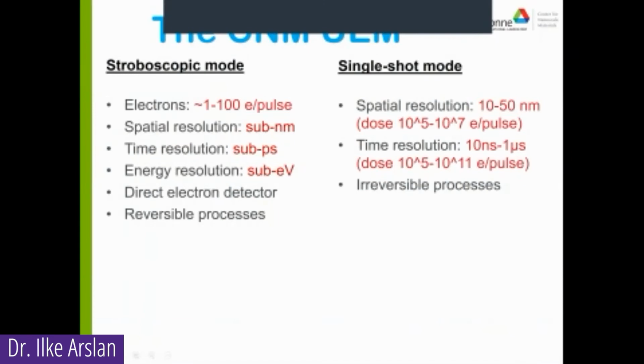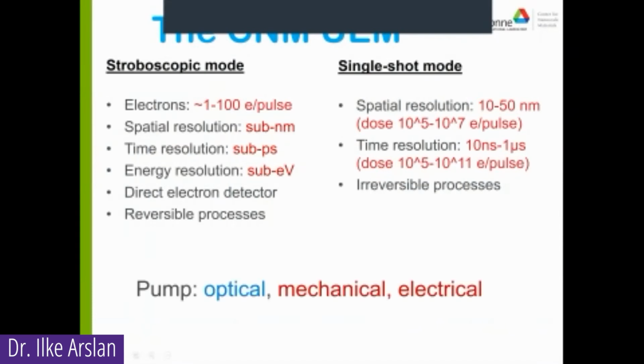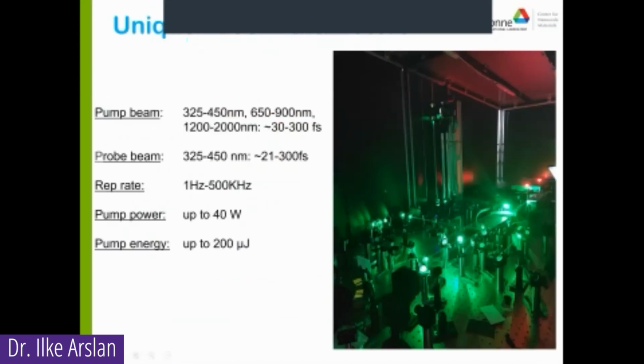But I'll just finish up by telling you that we can operate the UEM in these two different modes, but we're operating in stroboscopic mode. So we are looking at around 1 to 100 electrons per pulse. We can get sub-nanometer spatial resolution, sub-picosecond time resolution, and sub-eV energy resolution, but not all at the same time because the electrons don't like each other. We do have a direct electron detector, and the processes that we're looking at are reversible.